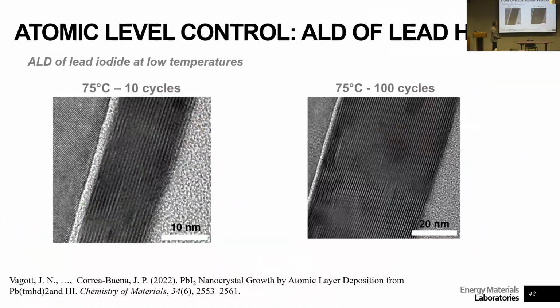The other thing that we're doing is developing some ways of depositing these materials atom by atom. So here is a very high risk project that I've been working on for the past 5 years since I arrived at Georgia Tech. How can we make organic-inorganic hybrid materials by atomic layer deposition? And so here's our first attempt to make the first step, which is the inorganic part, lead halide, which we can actually grow cycle by cycle. These are 10 cycles, and these are 10 layers of lead iodide. So one cycle gives us one layer, which is pretty remarkable for ALD.